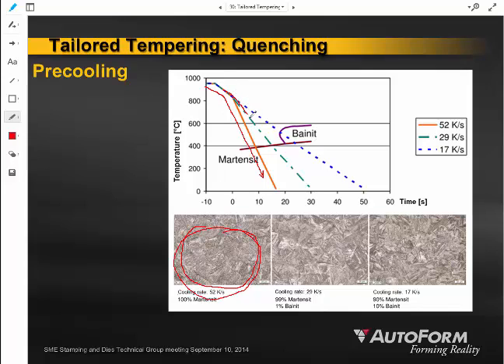If you cool the material a little bit slower, now you don't have 100% martensite. Maybe you end up with 99% martensite, 1% bainite, and that's going to give you a different characteristic in the finished part. And then if you cool this at a much slower cooling rate by holding that die a little bit warmer, then you're going to have maybe only 90% martensite and 10% bainite.